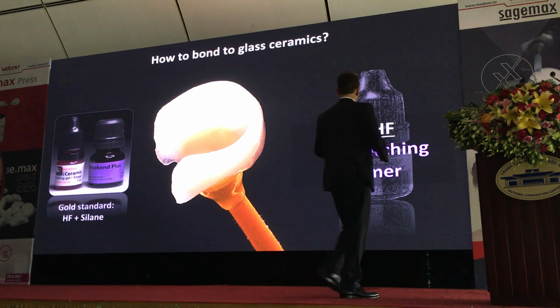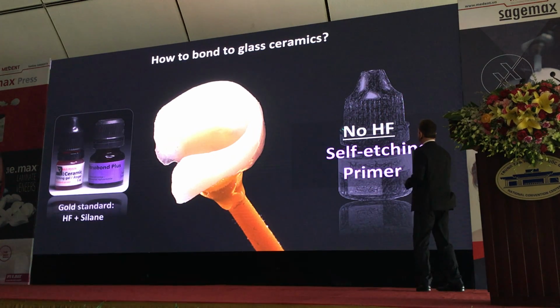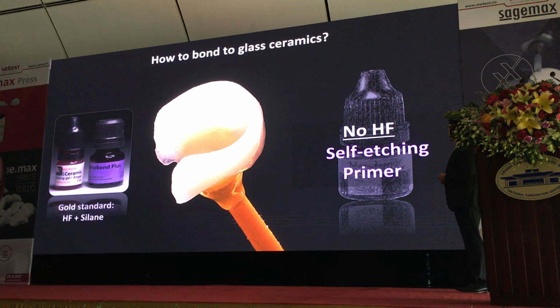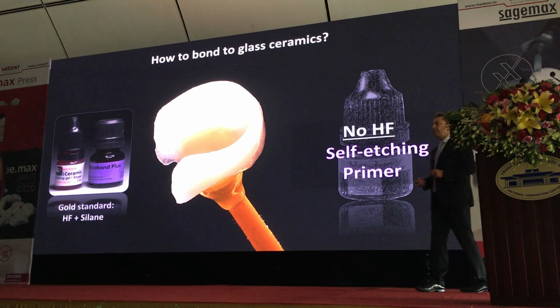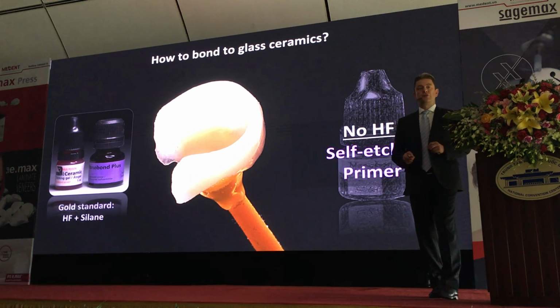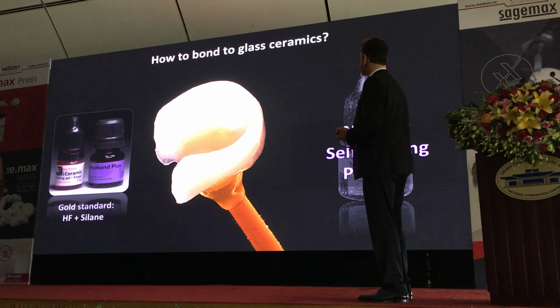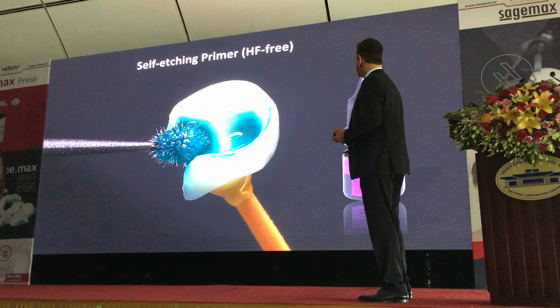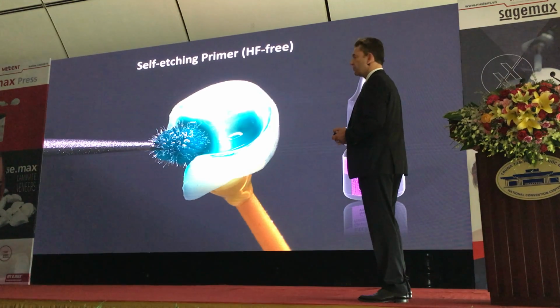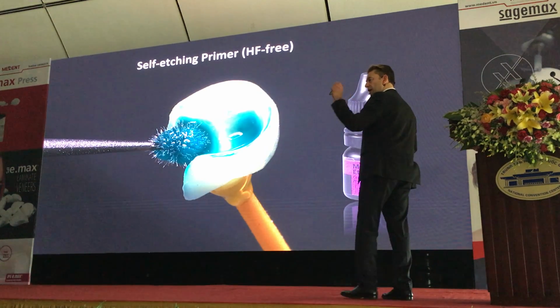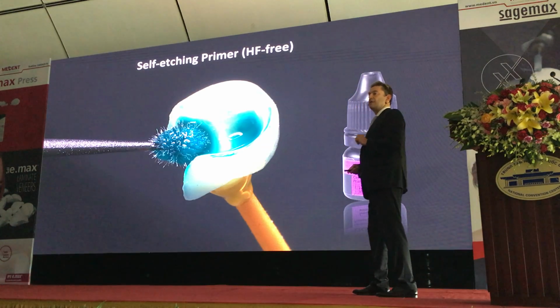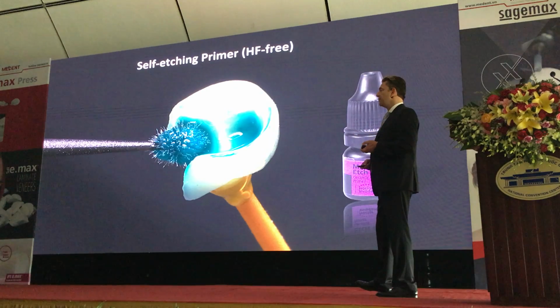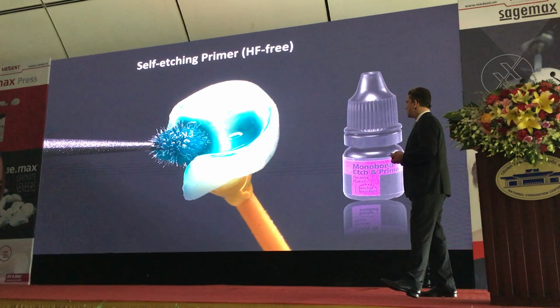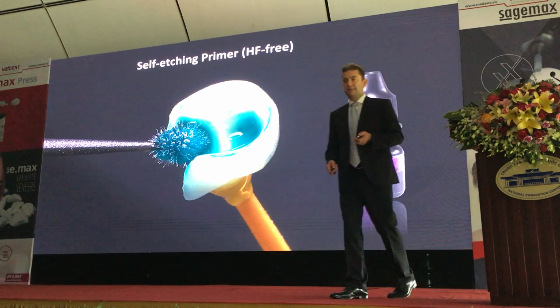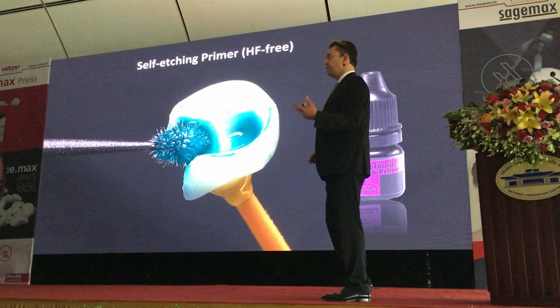But there is a new technique where you don't need hydrofluoric acid, and this is done with a special self-etching primer, and this is called Monobond Etch and Prime. So we can use this Monobond Etch and Prime here, and we just apply this on the inside of this restoration. Just scrub it in and leave it for another 40 seconds, rinse it off, and we're done. So you don't have to deal with hydrofluoric acid. That makes the whole thing much easier and less dangerous, because hydrofluoric acid is very poisonous.